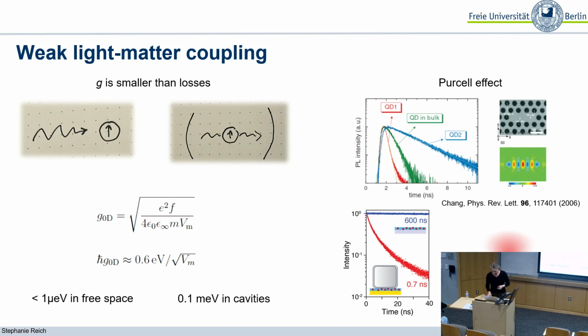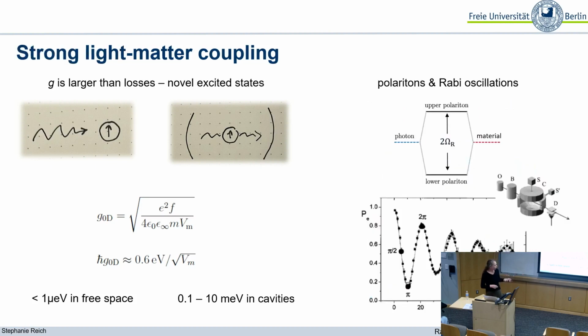Now, you can try to further increase light-matter coupling by making these cavities smaller and smaller. And if you go to so-called sub-wavelength cavities, where you confine the light more than you would normally think you're able to do, so you can do this with plasmonic structures, you reach a regime where the light-matter interaction strength becomes comparable to the losses that you have in your system. And if you're in this regime, you will call it strong light-matter coupling. And then something very interesting happens.